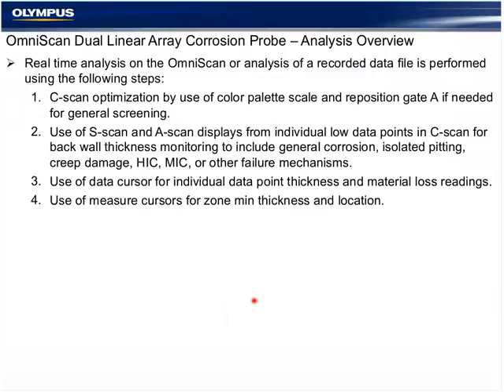Real-time analysis on OmniScan recorded data file for corrosion mapping requires 4 basic functions. The first is the C-scan optimization. We're going to adjust the color palette and reposition the gate if needed for general screening. Often during the inspection, we encounter problems that were not necessarily known prior to inspection that we would want to move the gate position and optimize the color palette.